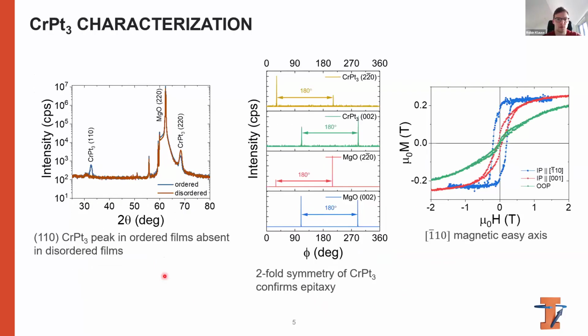To characterize the films, we used X-ray diffraction. For the disordered chromium-platinum-3, we see only the 220 peak, and there's no 110 peak. But for the ordered chromium-platinum-3, we also have this 110 peak, which is only allowed for an ordered crystal, and not for a disordered one.